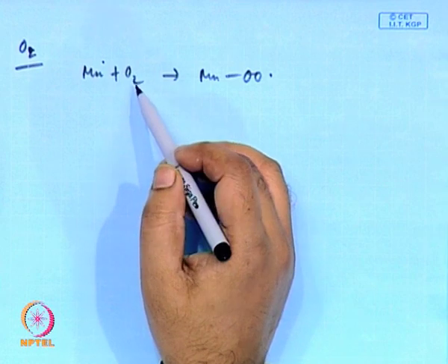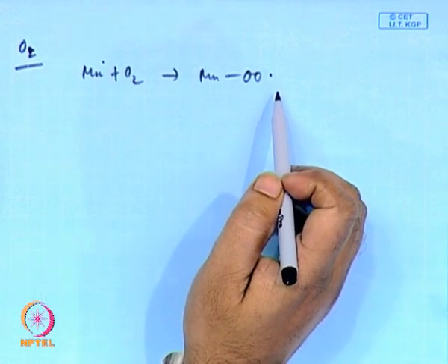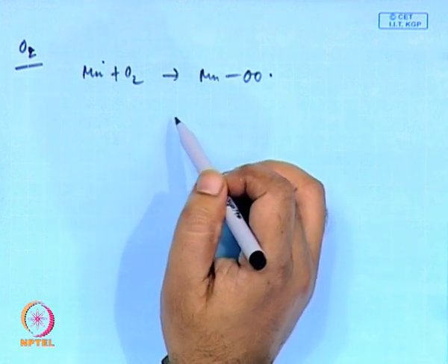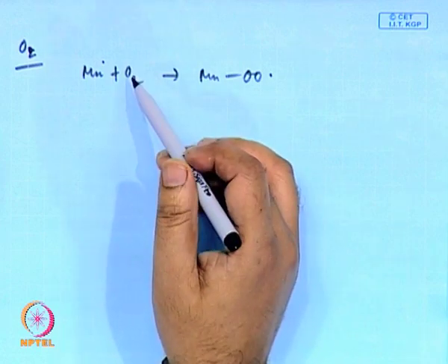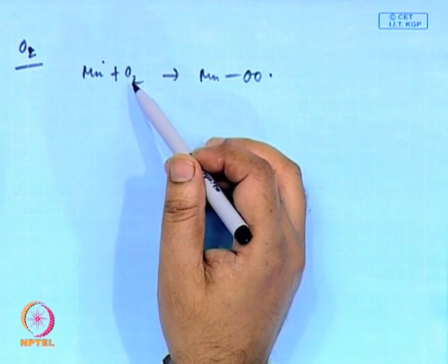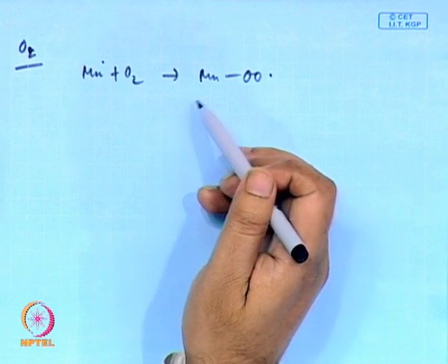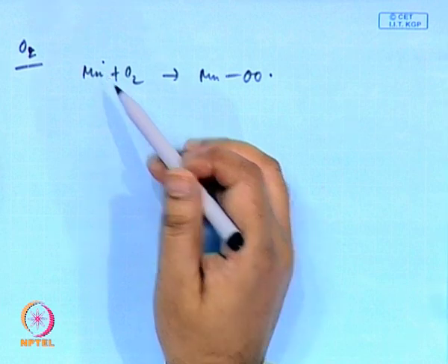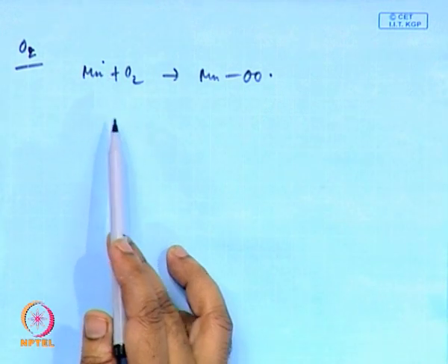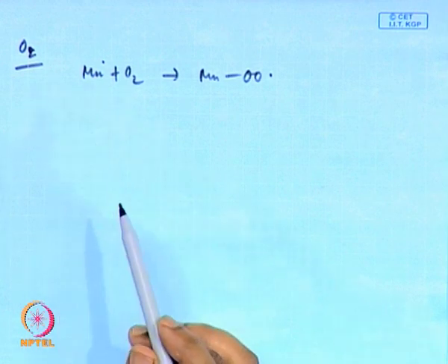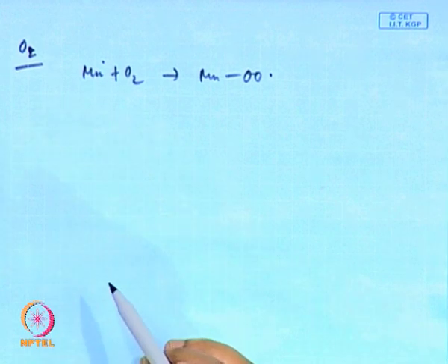That means the tendency of the oxygen molecule to undergo this reaction is extremely high. So, when you do a radical chain polymerization reaction, you must remove the oxygen molecule from the reaction medium as much as possible to avoid this killing of the propagating radical, by which it will stop the reaction and also reduce the molecular weight.